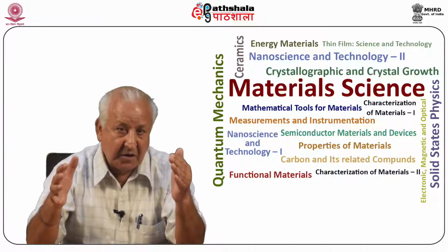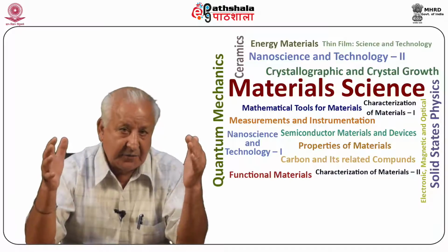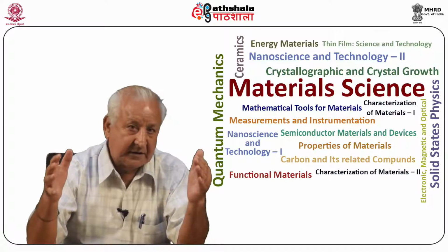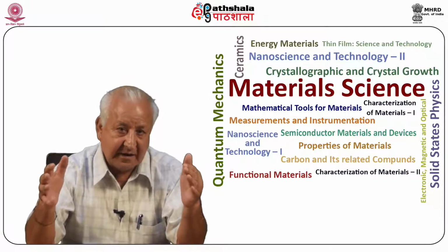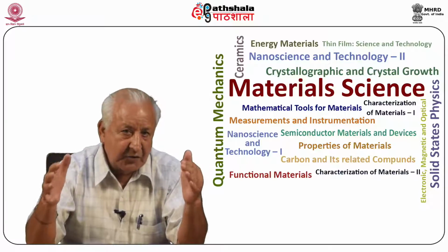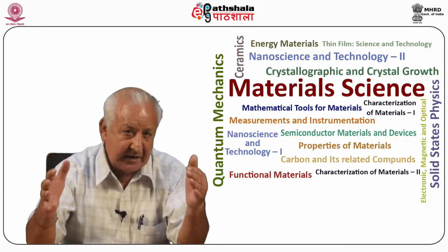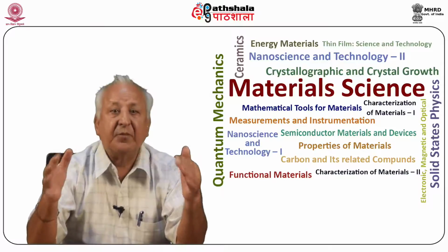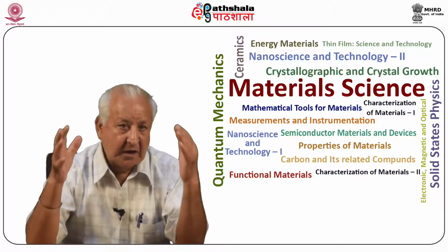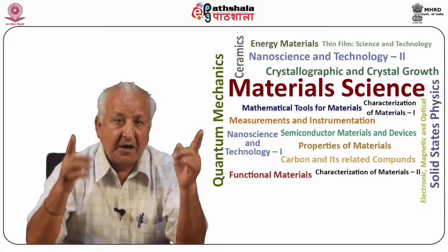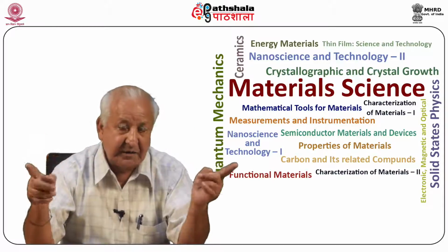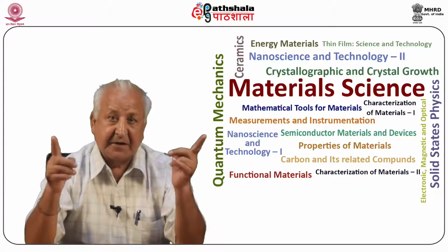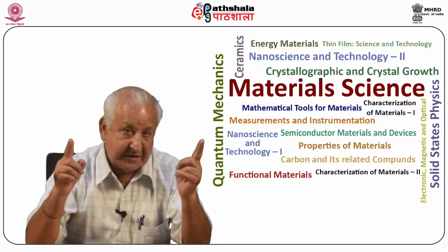Ideally, a crystal on application of stress deforms when planes of atoms slide over one another just like cards in a deck. We say 1 unit of slip on a slip plane has occurred if every atom on one side of that plane has moved into a position which was originally occupied by its nearest neighbor in the direction of slip. As such, the unit slip does not disturb the crystal perfection.